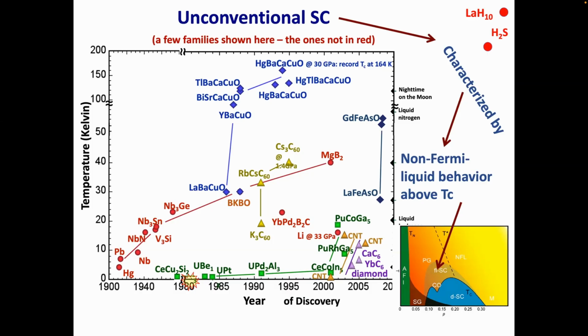I've left 50 different families of superconductors off this, but what unifies the unconventional superconductors isn't the order parameter symmetry. It's the breaking of the symmetry of the underlying lattice by the electron fluid above TC, whether it's quantum critical, stripes, or nematicity. We all know in a Fermi liquid, the electronic properties are determined by where the atoms are and what they are, and then you get the optical, thermodynamic, and transport properties. But we can't do that with all these strange phases above TC, which almost every unconventional superconductor has, whether it's d-wave or s plus-minus or whatever.